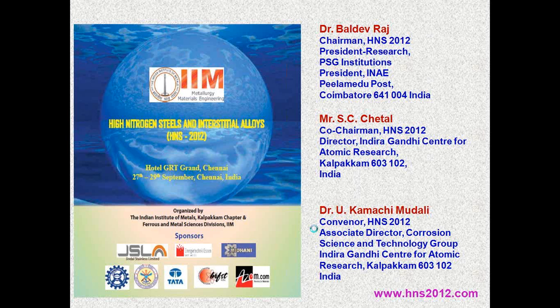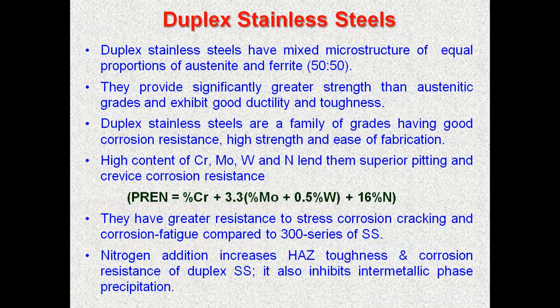Now, coming from austenitic to duplex stainless steels, they have a mixed microstructure. Austenitic stainless steels are gamma phase FCC structure, whereas duplex stainless steels are a mixture of austenite and ferrite, 50-50. They provide significantly greater strength than austenitic grades and exhibit good ductility and toughness. There is a family of grades having good corrosion resistance, high strength and ease of fabrication.